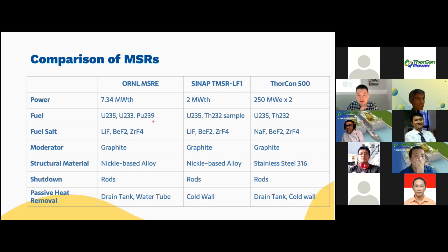In terms of fuel, the MSRE has used uranium-235, 233, and plutonium-239. The SINAP one is going to use uranium-235. They don't have uranium-233, but they're going to use thorium as a sample, which means the thorium fuel will not be mixed with the fuel salt, but rather it will be put into a channel to be irradiated as a sample. While the Thorcon 500 uses both uranium-235 and thorium-232. And as for the fuel salt, the ORNL is using lithium fluoride, beryllium fluoride, zirconium fluoride. And the SINAP one has exactly the same fuel salt composition. The difference on the Thorcon is it replaced lithium fluoride with sodium fluoride.